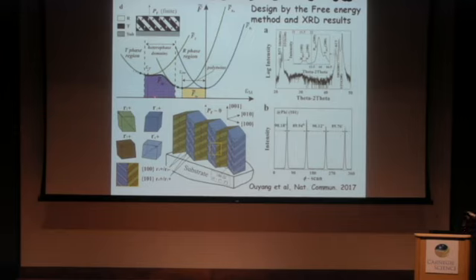So this is one of the typical XRD results. I show you the XRD results of this BZT film grown epitaxially on strontium titanate. You can see very nicely all these 00L peaks, and you can see actually there are two peaks on the BZT. One is tetragonal, one is rhombohedral, and we did phi scans of both peaks, just showing you nice four peaks, indicating the epitaxy quality of the film.